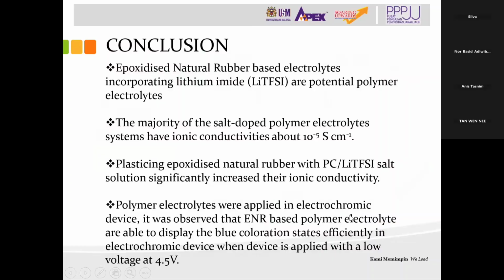So as a conclusion, from my research for electrochromic device application, epoxidized natural rubber-based electrolytes incorporating lithium imide are potential polymer electrolytes. The majority of the salt-polymer electrolyte systems have ionic conductivities of about 10 to the power of -5 Siemens per cm, and plasticizing epoxidized natural rubber with PC and lithium imide salt solution significantly increases their ionic conductivity. After we add the plasticizer, we have higher ionic conductivity for the polymer electrolytes.